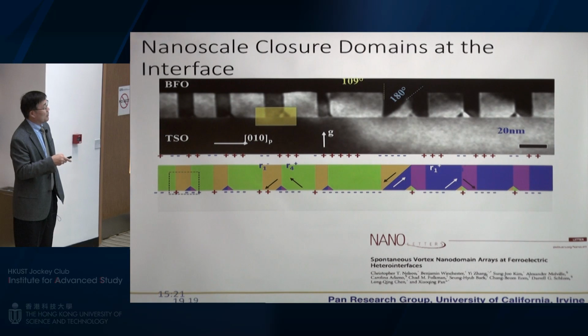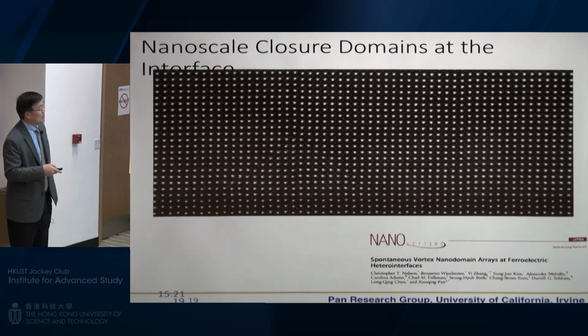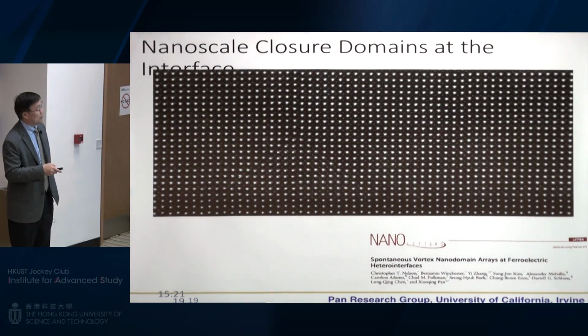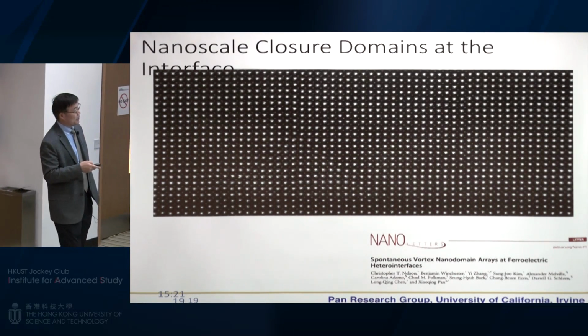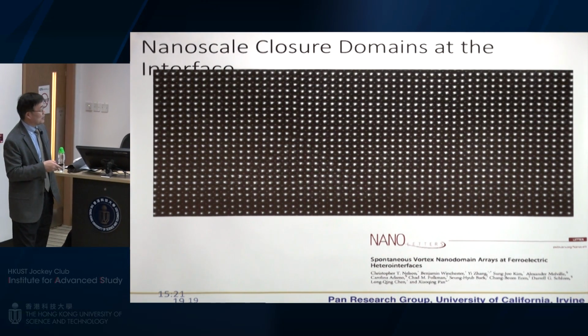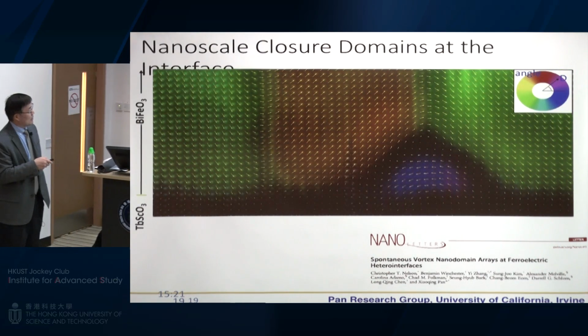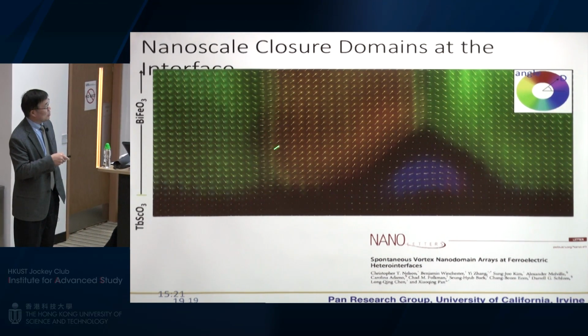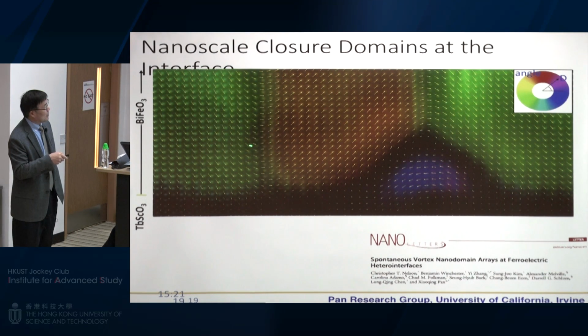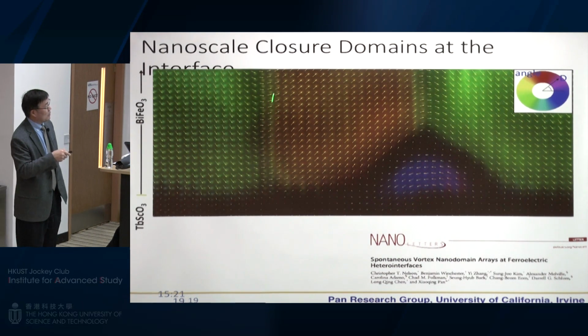We just focus on this area, with a two-domain wall termination, one without a defect and another with a defect. Then we get a high-resolution image and use the method I just explained to map the polarization from unit cell to unit cell. Then you can see the dipole moment changing from this direction to that direction by a rotation of 90 degrees in the plane. This domain wall fits perfectly into the bulk crystal structure. So it's a perfect 109 degree domain wall.